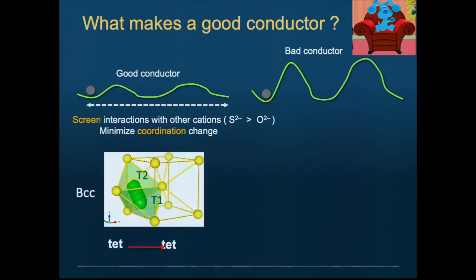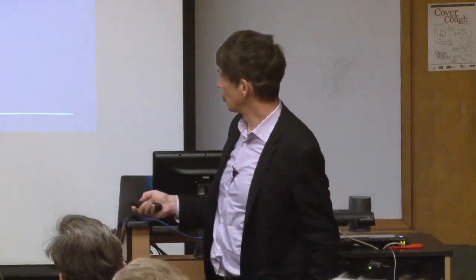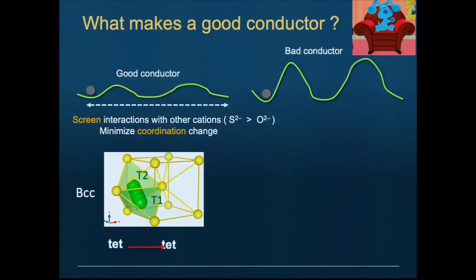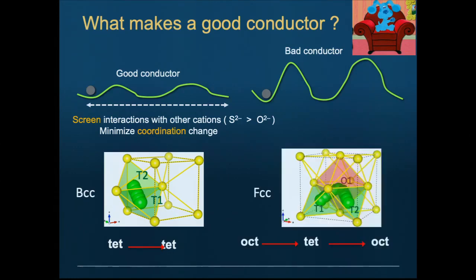And that was a key insight, because we started looking at different packings of anions, and something that you probably teach in freshman material science became suddenly very important: if you look at BCC versus FCC, they have very different interstitial void counting. So if you have BCC, you have a lot of tetrahedral voids that share faces with each other. Whereas if you go to FCC, remember, lithium prefers mostly tetrahedral sites. If you're in a tetrahedral site, the only way to get to another tetrahedral site is to go through an octahedral site. So based on what I just told you, what's going to be the better conductor, right?